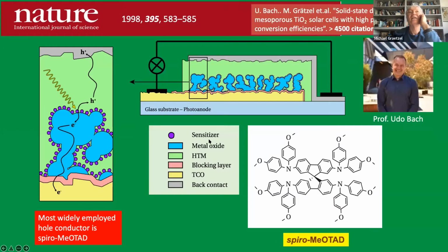That is, the sensitizer is now contacted by this organic hole conductor, which is a triarylamine type molecule, and it's called spiro-OMeTAD. This actually was developed first for dye-sensitized solar cells, and there's a Nature paper we published in 1998 with Udo Bach as the first author. He was my graduate student at that time. He's now a professor at Monash University. And this has now become the most widely employed hole conductor because it matches so well, not only for the dye-sensitized liquid cell, as a replacement for the electrolyte, but also for perovskites. And today's record cells, the ones that get, say, to 25.7%, we are still using this so-called spiro hole conductor.